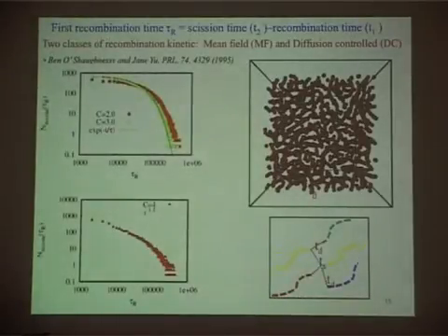Correct. Okay, so now we also look at the recombination time, the fission and recombination time, which we can measure here. Basically the recombination time is the time at which, so you start the clock when some bond has a scission. Okay, and then you ask the question, when does it recombine again, with itself or with something else? That's the time which we count. So that's a distribution of the recombination time, and that follows exponential. There have been papers by Ben O'Shaughnessy and Jane Yu, which explain why this would be exponential in that regime.